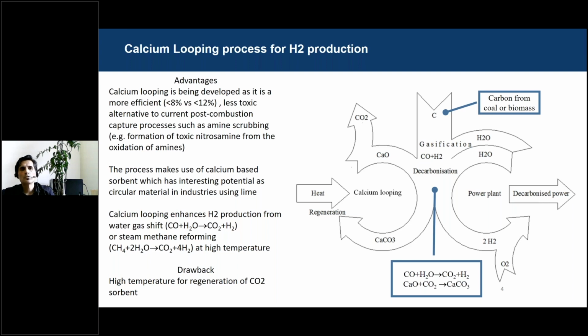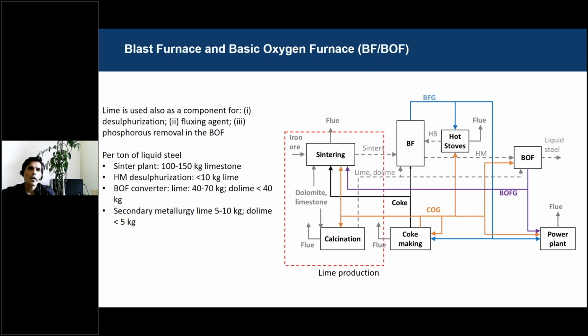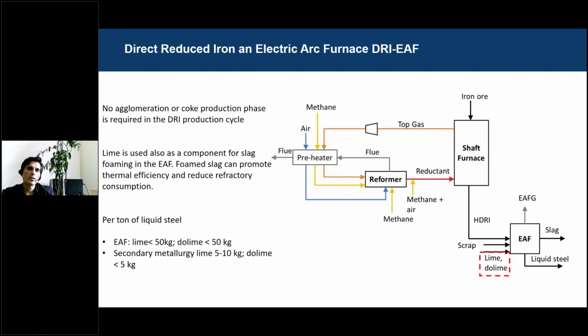Let's see how to integrate the calcium loop in the steel industry. Here I report the well-known blast furnace and basic oxygen furnace cycle. In this cycle, a solid mixture of sintered material composed of iron ore, coke and lime is used to feed blast furnaces as flux, but also basic oxygen furnaces in order to prevent any damage of the liner of the inner part of the basic oxygen furnaces. The hot metal produced in the blast furnaces is sent to the basic oxygen furnace, where it is converted into liquid steel. The alternative option to the blast furnace, basic oxygen furnace, I mean BF-BOF, is the DRI-EAF, the direct reduced iron process coupled with the electric arc furnaces.